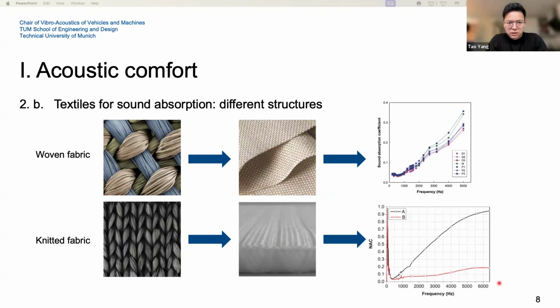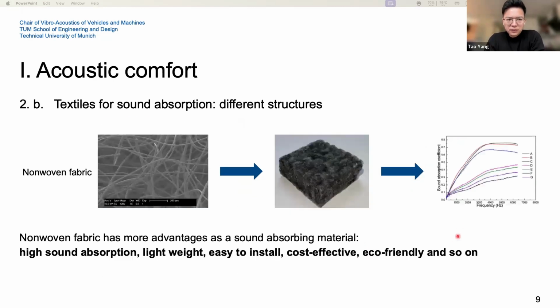If we talk about textiles for sound absorption, we can look at different structures. For example, textiles can generally be categorized as woven fabric, knitted fabric, and non-woven fabric. But because woven fabric is always very thin, it has very poor sound absorption, so it is not used much for sound absorption. For the knitted fabric, there is a special technology that can generate very thick structures. For example, this fabric called space fabric can reach 20, 30, even 40 millimeter thickness, and then it achieves good sound absorption compared to the woven fabric. Actually, compared to the knitted and woven fabrics, the non-woven material is dominant in the market so far.